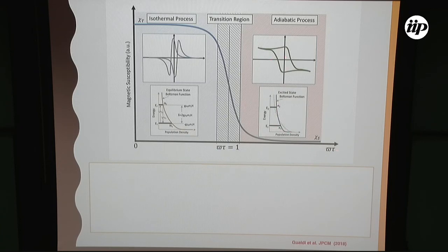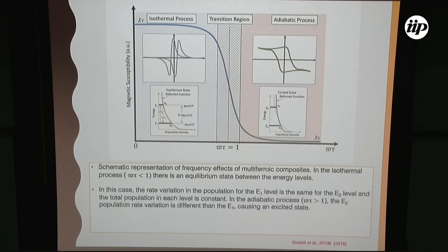So, when the frequency increases, the change of the levels and the states in the equilibrium state is different. This is associated with when omega tau is more than 1, a change in this process. This magnetoelastic effect is very important owing to the difference of the total angular momentum and the spin-orbit coupling, which in the case of nickel ferrite is absent.